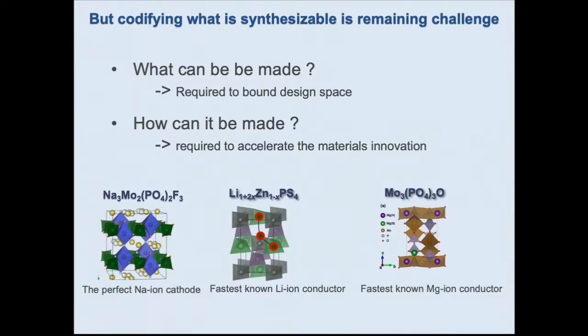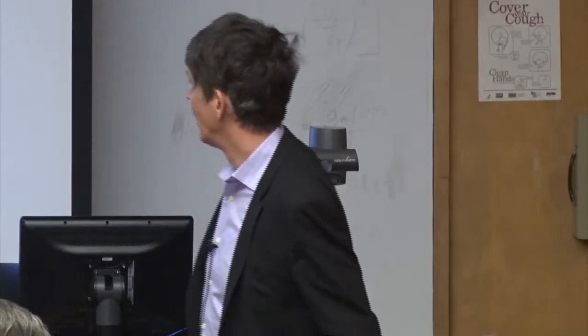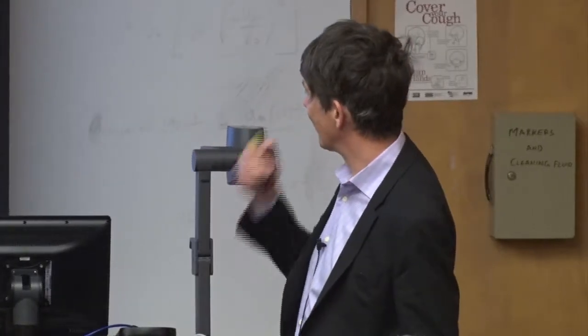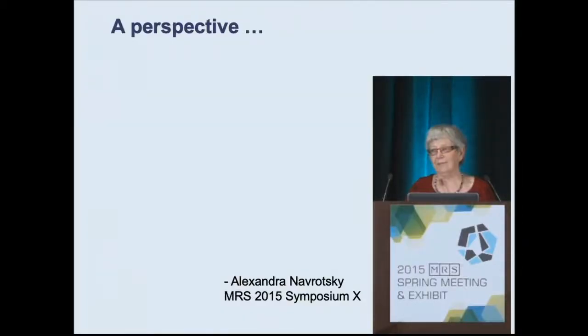Lithium zinc thiophosphate, this is predicted to be the fastest known lithium-ion conductor. I mentioned that yesterday. This one is crazy. This would be the fastest known magnesium-ion conductor. This would be a magnesium-ion conductor that is as fast as a lithium-ion conductor, which is truly remarkable, right? Because it's a divalent ion. That is a metastable phase predicted, so nobody knows how to make it. Okay, so when you talk about synthesis, right, people sort of go like, well, you do thermodynamics, and this is all kinetic, so you have nothing to tell me, right? And I like to quote Alexandra Navrotsky, who has a perspective on this.